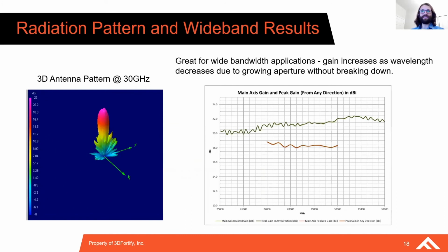The chart on the left shows the 3D antenna pattern of the lens at 30 gigahertz. And the right chart shows the amazing wideband performance of the lens from 25 to 32 gigahertz. The gain increases as the wavelength decreases, which is due to the growing aperture without breaking down. The red curve on the chart also shows a lower performance of the traditional photopolymer across several frequency bands. This wideband performance is excellent for devices in the Ka band, making it an interesting and intriguing option for 5G millimeter wave applications, as well as satellite communications or radar.